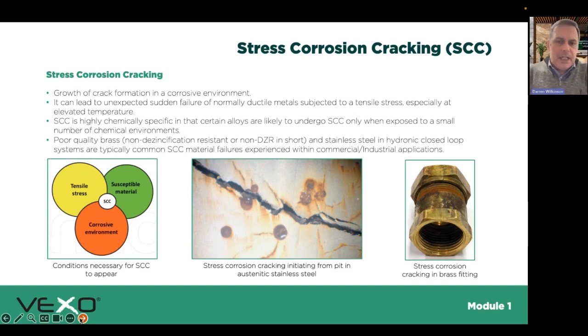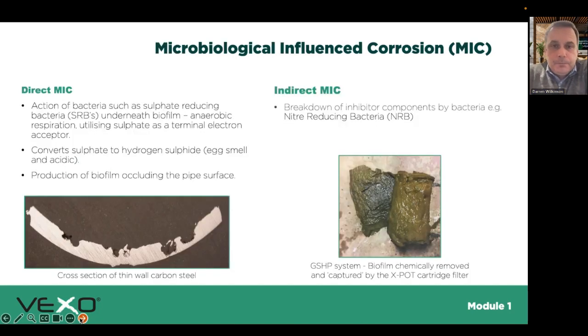We need a susceptible material. So in the case of a chill water system, it will be, say, chill water typically. You may have had a bacterial issue, and as a byproduct, they create ammonia. And unfortunately, that ammonia becomes part of the corrosive environment for the system. So the susceptible material in this case would be a brass fitting. Don't see it as often, and certainly see it a lot less than we used to nowadays, because there's DZR brass. But there was a period where engineers would specify bronze on chill water just to be completely covered, I suppose, rather than a brass. And if you have a poor quality brass, you could have failures. Whereas now, there is the EN standard for brass to be dezincification resistant. So a much higher quality and a lot less alloys in there, like zinc, for example, that would normally be stripped out by the ammonia, leaving porous copper.